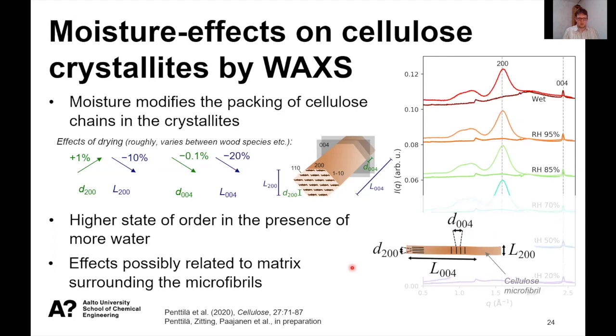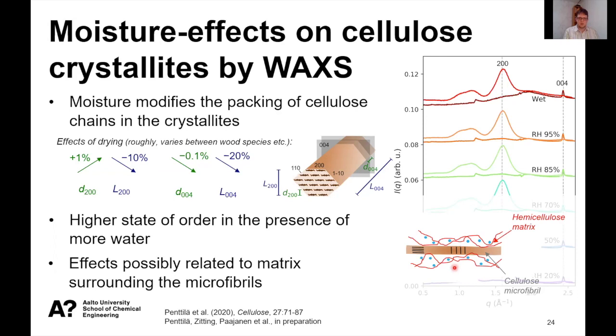This indicates that the state of order in the crystallites is actually higher in the presence of water. This has been observed with other methods as well, and it could be related to drying-induced stresses in the structure. One possible mechanism is that the cellulose microfibril is covered by hemicelluloses which are hydrated; when water is removed, the hemicellulose matrix shrinks, contracting the microfibril in the longitudinal direction, and due to the adjacent microfibrils on both sides it kind of pulls the crystal apart in the lateral direction.